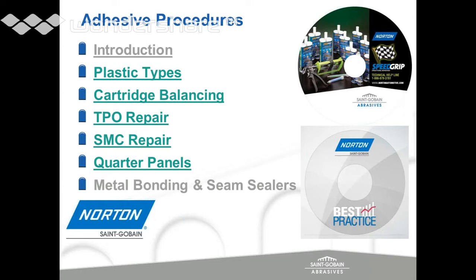But the neat thing about the product is it's urethane based, so it makes it very user-friendly. It can be used on metal, it can be used on plastic. As a matter of fact, there are 2 materials we recommend you don't use it on, and there are only 2 because of the strength of the structural adhesive. This urethane product has 3,700 pounds per square inch tensile strength, which is almost twice as strong as a resistance spot weld. So we recommend you don't put in windshields with it or any type of glass that is expected to come out someday, because the only way you're going to get the glue out or off is to heat it to 240 degrees Fahrenheit or to physically cut it or grind it out.